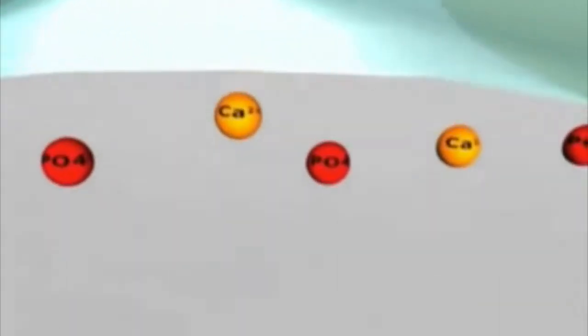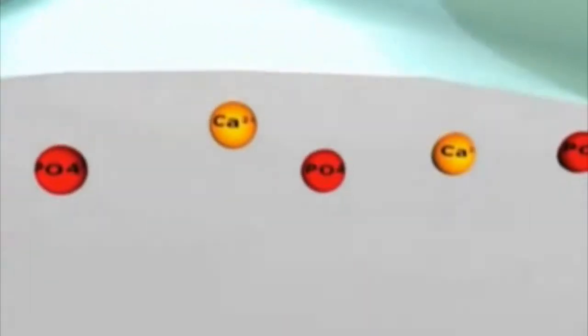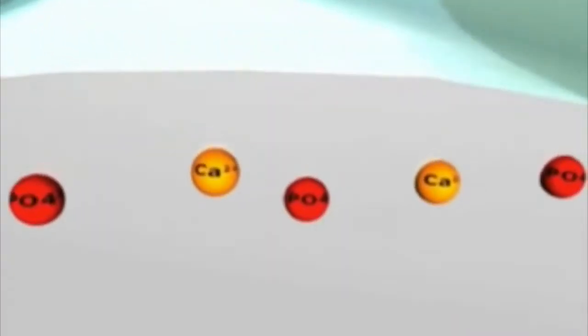Glass ionomer cements mature over time. However, their final strength is further enhanced by exposure to saliva after their initial setting reaction. Calcium and phosphate ions from saliva are able to penetrate into the set glass ionomer matrix, and this uptake further hardens the cement structure.